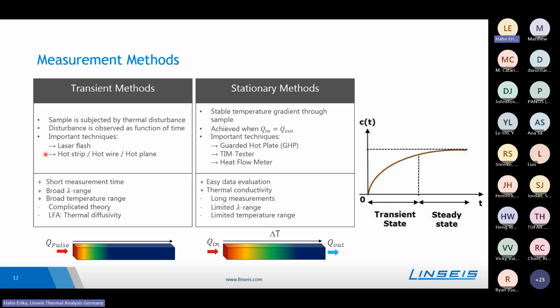Well-known transient methods are the laser flash technique, as well as the techniques which all rely on the hot wire technique. As already mentioned, the advantage is that the measurement time is quite short. One can cover a very broad thermal conductivity range. The disadvantage here is that the theory for the evaluation is mostly quite complicated. In case of the laser flash, the LFA, the disadvantage is that one cannot determine the thermal conductivity directly, but will get out the thermal diffusivity of the test.